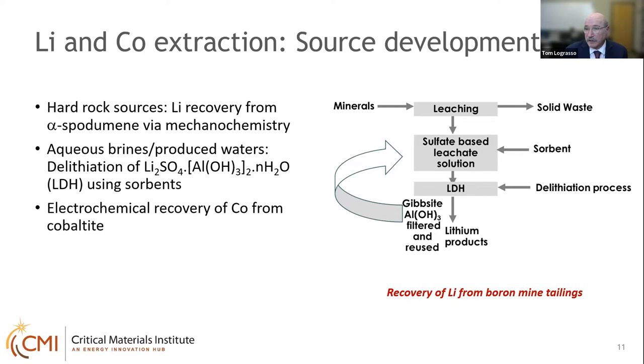In this particular site, it's the boron mine tailings that have a rather high concentration of lithium. Taking the lessons we learned from the sorbents, we've been able to develop a sorbent based on gibbsite. It's very effective in selectively removing lithium from the sulfate-based leachate solution and concentrating that. The real question was, did the sorbents we developed for brines, which is typically chloride chemistry, work in sulfate? And we've been able to do that.